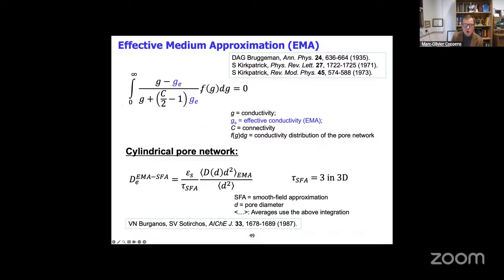It's an integral over the conductivity distribution, which is related to a pore size distribution. So if these are pores, you can have models that relate to the local diffusivity and the diameter of these pores if it's a cylindrical pore. And so you can actually calculate the effective conductivity or the effective diffusivity, including the connectivity C of this network. So this is a very elegant theory, and it works incredibly well in many situations, especially if you're far enough from the percolation threshold. So if you have a poorly connected network, low connectivity, and you're close to the percolation threshold,